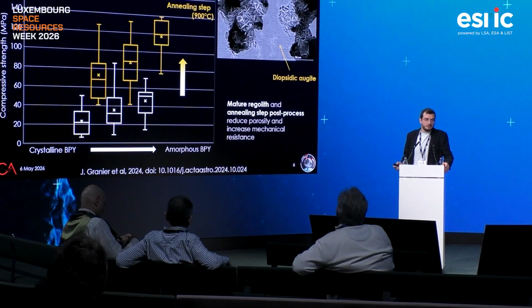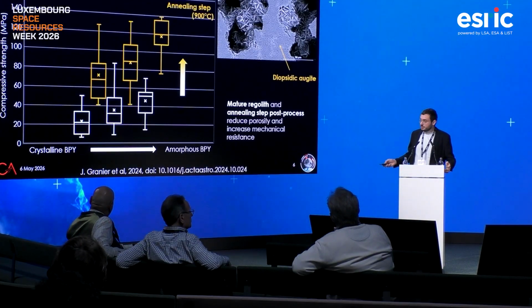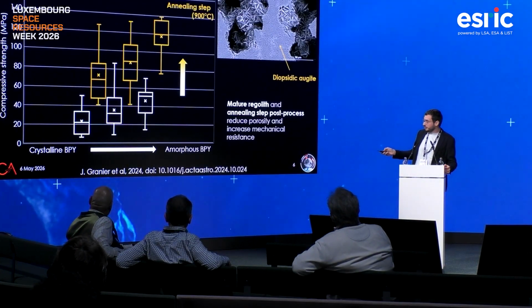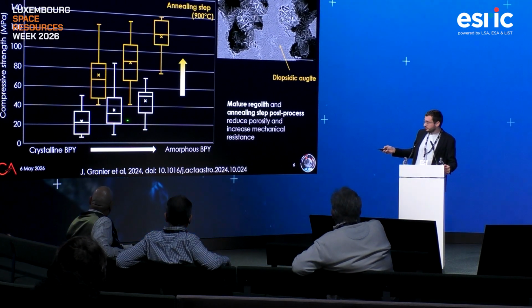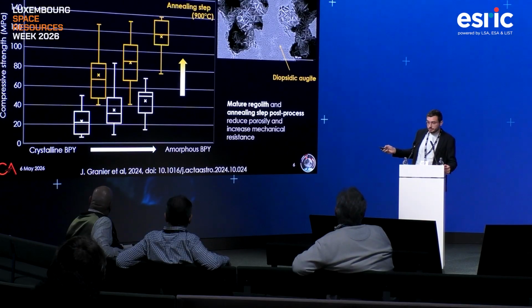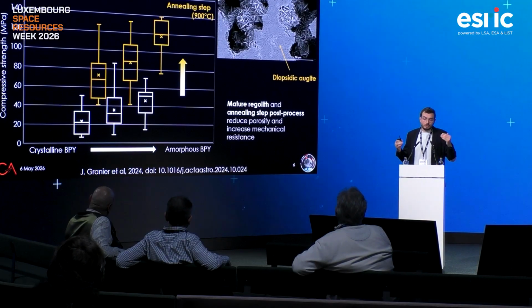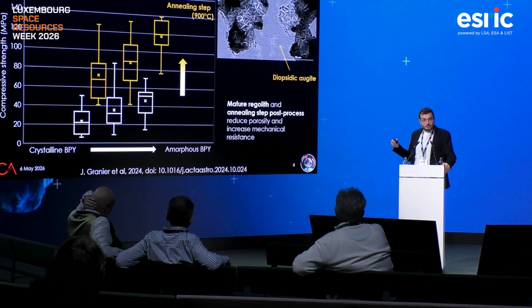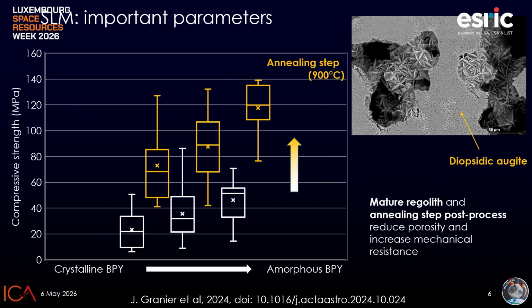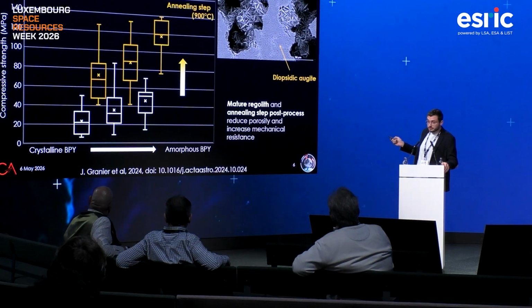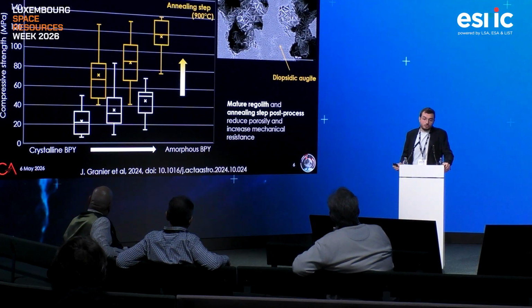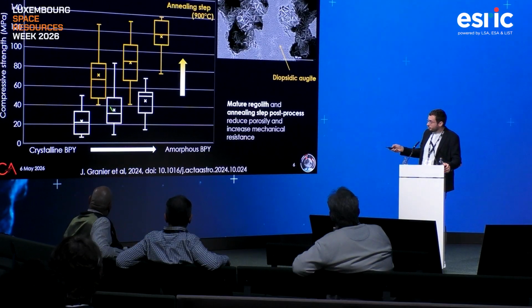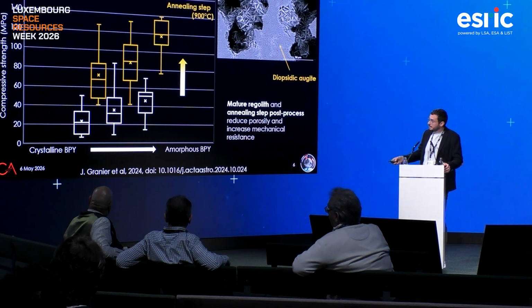Especially during my PhD, we found 2 important parameters. The first one is the amount of amorphous powder you have at the beginning in your mix. Starting from a 100% crystalline powder to a 100% amorphous one, you can see that we really increase the compressive strength of our samples. It's because you homogenize the sample and you lower the melting point. Then in a second step, if you take your samples at the end of the process and you anneal them at 900 degrees, so you have your glassy samples, and then you recrystallize them, you get this kind of microstructure, this network of diopsidic augite, which is quite more resistant, as you can see here, when you move from the white compositions to the yellow one. We really multiply the compressive strength of our samples.